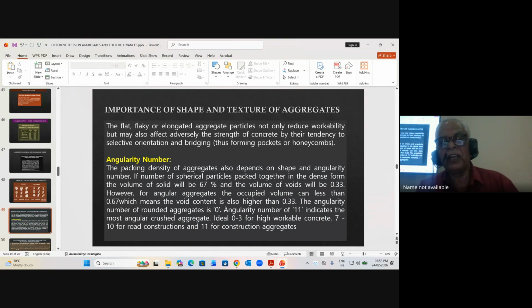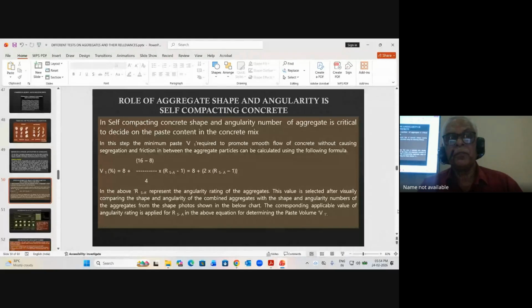So aggregate angularity number is counted from 0 to 11. 0 means rounded aggregates. Angularity number 11 indicates that most of it is crushed aggregate. Ideally, angularity number 0 to 3 is for high workable concrete, 7 to 10 for road construction, and 11 for normal construction of buildings. These are the limits you can consider. It's not given in the IS standard, but it's a general norm based on literature and studies.